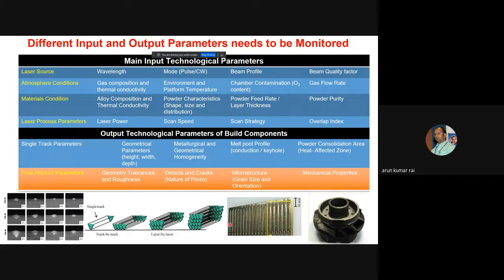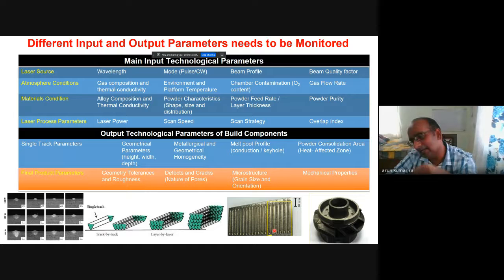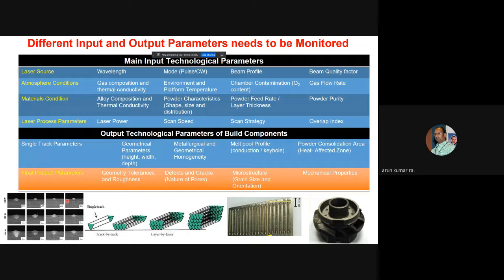These single tracks are deposited, and then based on the single track information, we cut this along the cross section and see the melt pool profile. You can see here the melt pool profile with respect to laser power. If you come from the top to bottom, you can see the laser power being increased from 100 watt to 195 watt. You can see that with increasing laser power, the depth of the melt increases. This is basically conduction.